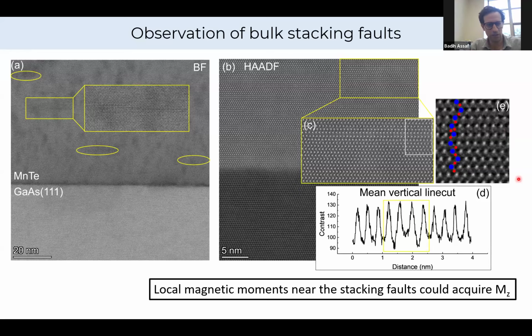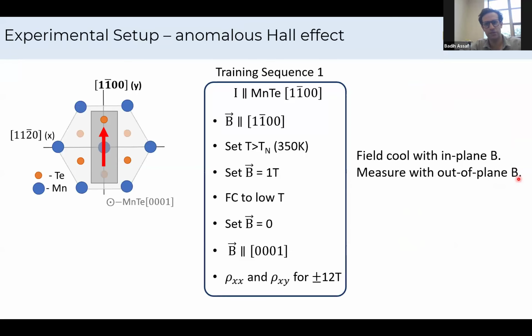We actually measured it in a slightly unconventional way. Instead of simply sticking wires onto your sample and measuring it, we did that, but we also figured out a training sequence. And we tested that training sequence where we cooled down the manganese telluride thin films under a magnetic field before we measure them. And we can apply a field along the easy axis, along 11 bar 00.